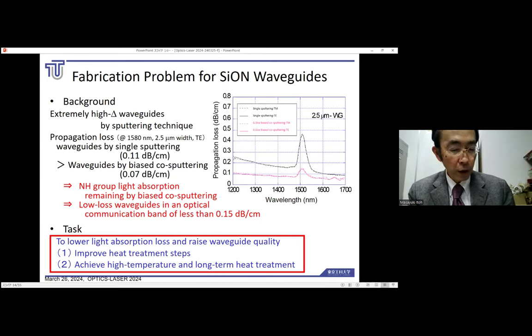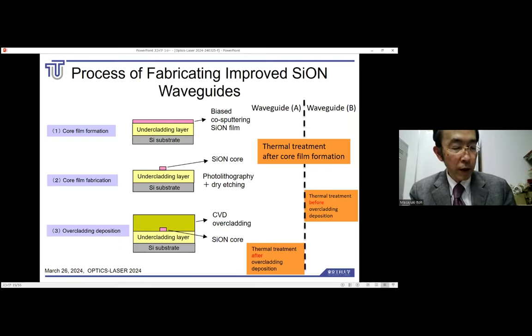Therefore, we are considering the following measures to reduce absorption loss and improve the quality of extremely high delta silicon oxynitride waveguides. First, improve the heat treatment processes. Second, achieve high temperature and long-term heat treatment. We searched for the key points by conducting experiments under different conditions for the above 2 points. This is a process of fabricating silicon oxynitride waveguides. Two heat treatment processes are prepared to densify and improve the quality of silica-based glass, and different conditions are applied to waveguide A and waveguide B. First, undercladding is